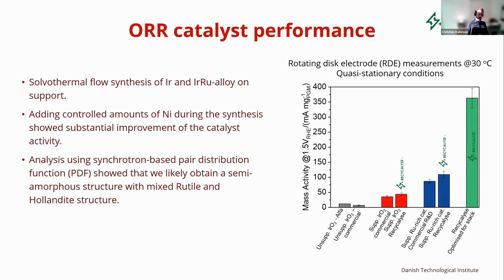and I was going to skip to this directly. What we see is that just from utilizing support, we can increase the activities of these materials quite substantially, also compared actually to commercial state-of-the-art supported catalyst. But actually, by introducing a small amount of nickel during the synthesis, we can obtain a semi-amorphous structure with a mixed rutile and hollandite structure, and that means that we can really increase the activity of the catalyst. The nickel is leached out afterwards. This activity we need to also utilize in the MEA structure.